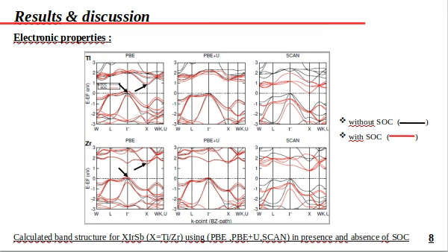However, when comparing the calculation using the SCAN functional in the absence of spin-orbit coupling, we observe a good performance of the SCAN functional for the ZrIrSb compound, while in the case of the TiIrSb compound, it seems that PBE+U plays a better role in describing the band gap than the SCAN functional.